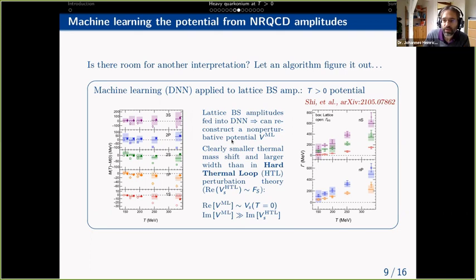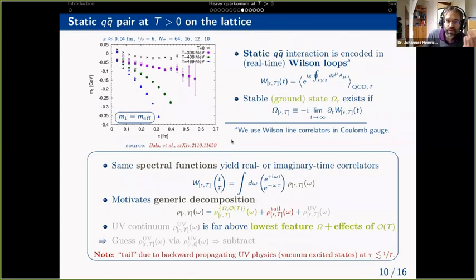After that, we went on and tried to study this with static quarkonium. Here, the idea is that you have a Wilson loop in real time. You can look at whether that has a stable ground state, if in the large time limit the time derivative becomes time independent. Since we can't do a real-time calculation, we do an imaginary time calculation. In this case, for the imaginary time, it would mean, like the black symbol showing here, that the so-called effective mass becomes flat at large times.